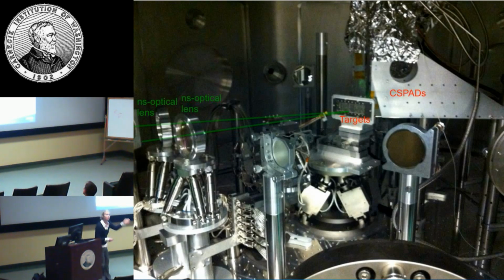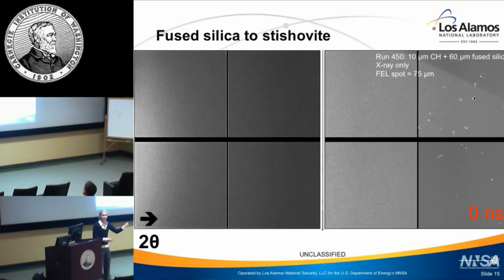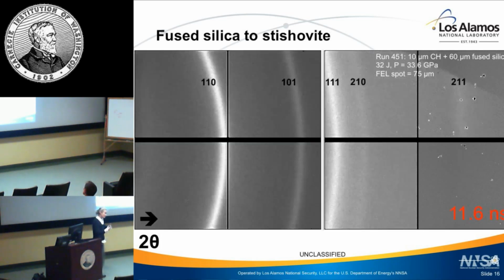So now what happens when we launch the shock and I probe at a particular time delay? We see this beautiful diffraction, okay? It's fairly smooth. These peaks, I can then index based on position. I can index them as pure stishovite, okay? So we're seeing fused silica transformed to pure stishovite. This is at a time delay almost 12 nanoseconds, okay? So our shock front has pretty much traversed our entire sample.